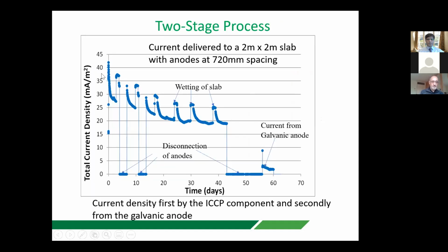And in the laboratory, we had a go at simulating this, and this is some of the results. We could induce quite high corrosion current densities from the battery, over 20 milliamps up to 40 milliamps and so on, but it's a reducing trend. This occasions when we were wetting the concrete and therefore delivering higher current. And here we disconnected the anodes and measured the polarisation. And this is the galvanic anode taking over. So you can see that there's a big drop in current output, but it's still within the level that is required for cathodic prevention. So it's the first very large amount of current delivery, try and stop corrosion, and then a maintenance of the galvanic element.